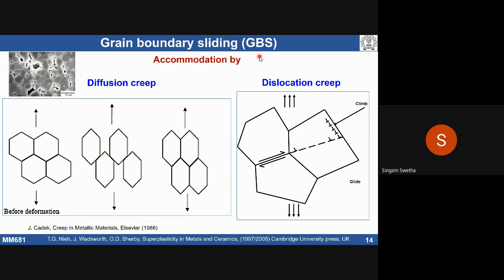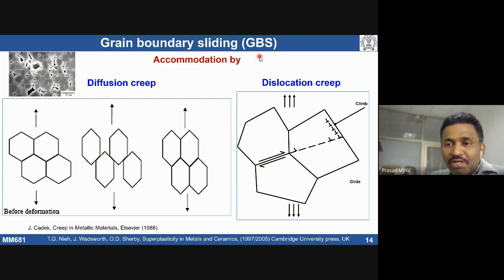So that means without changing the grain shape, we are observing elongation. If there is minimal shape change, we can get very large elongation. Here we do see some elongation of the grains, but by the time it becomes elongated grains, already a lot of grain boundary sliding has taken place. That can lead to very large strains. So among these two accommodation mechanisms, the dislocation creep mechanism can lead to larger strains than the diffusion creep accommodation.